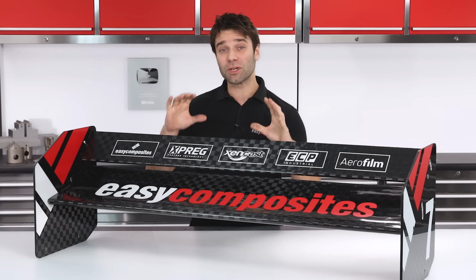When bonding aluminium directly to carbon fibre, you should decide whether galvanic corrosion is likely to be a problem in your application. As this is a wing on a dry stored race car, I'm not taking any measures as the wing will not be in the presence of any electrolytes that would facilitate the corrosion. But if your application does, maybe in a marine or conventional automotive application, then you should electrically isolate the carbon from the aluminium. The easiest way to do this is to laminate a thin layer of glass fibre between them. We'll set these to one side now for around 20 minutes to let the adhesive get to a good hold strength.